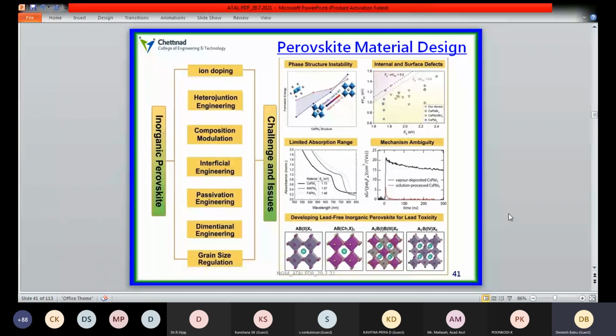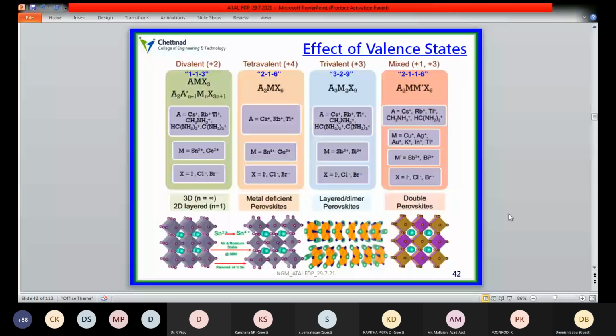The most important point is the composition of lead and cesium. Lead is the most toxic one, so we must identify an alternative to replace lead-based materials in these perovskite systems. That must be a wide research area in perovskites. As I mentioned earlier, divalent, tetravalent, trivalent, and mixed valent states are used for the fabrication of different structures, especially two-dimensional and three-dimensional layered perovskites, metal-deficient perovskites, dimer perovskites, and double perovskites also.